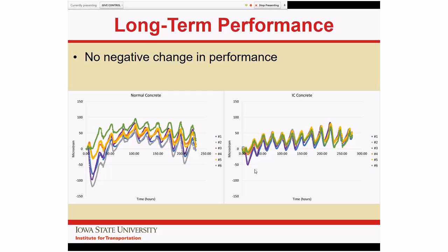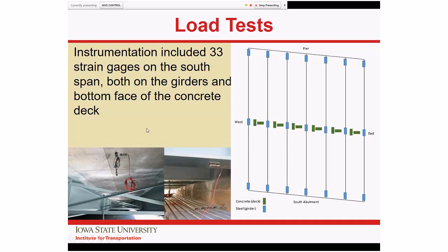But basically, what we were seeing is that slightly less variability in movement between the conventional concrete and the internally cured concrete. So again, expected diurnal temperature-related movements and much less differences top to bottom between the top and the bottom of the deck. So again, not a huge change, but the change that there is for the good.